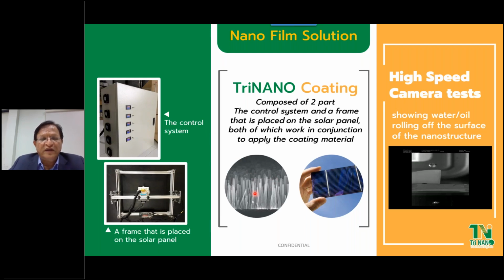Now, when we are talking of a thickness of 0.4 micron, which is thinner than a human hair, this is not visible to the human eye. And besides, the coating is colorless. Now, the third one is the anti-soiling. So we have a microstructure like this, whereby we increase the surface tension. So when anything falls on it, let's say watermarks or oil or dirt, it doesn't get stuck. It doesn't get flattened out. It forms a globule. So there is a single point of contact with the glass surface, and therefore you can use high pressure air or just a very soft brush to brush it off.